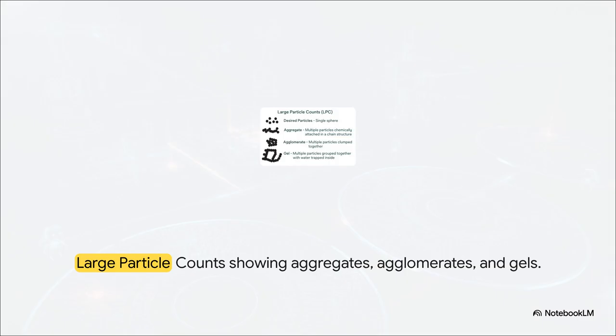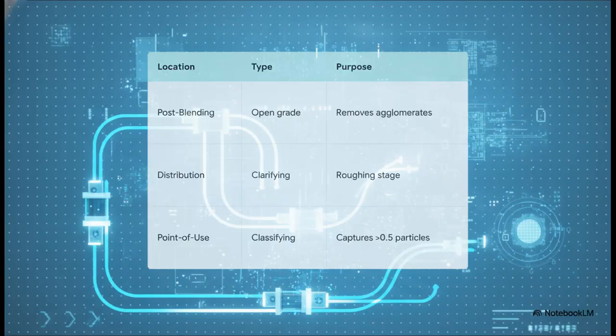But over time, maybe due to temperature changes or excessive shear from pumps, these particles can settle and clump together. They form aggregates, agglomerates, or gels with water trapped inside. In the industry, these are known as large particle counts, or the PSD tail, basically oversized particles greater than 0.5 microns. And if these hit the wafer, they act like boulders, catastrophically scratching the interlevel dielectrics and completely destroying the chip. Defeating these particles requires a highly engineered slurry distribution system with really elegant filtration at 3 specific locations.